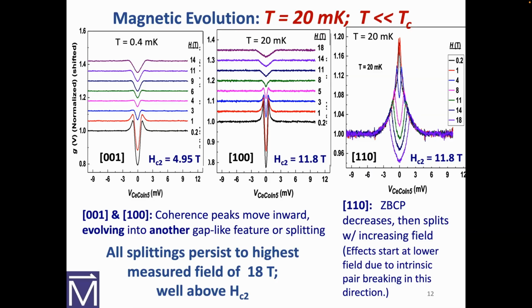Let's look at the left side. We have the 0, 0, 1 direction at low temperature and just enough magnetic field to drive the lead normal. So what we're seeing there is the tunneling density of states showing the superconducting gap of the cerium cobalt indium 5, just as we would expect. As you start raising the field, HC2 is about 5 Tesla, and the green line is 6 Tesla. Going from 0.2 Tesla, where the cerium cobalt indium 5 is superconducting, all the way up to 14 Tesla, there's no superconductivity up there.